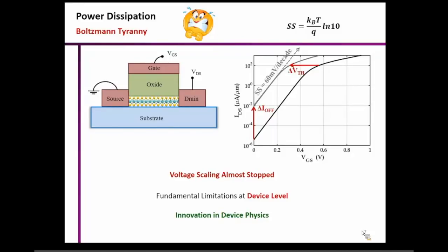And when you do that, you actually run into the problem of high leakage current. That increases your power dissipation in the device. And this is a bottleneck because your subthreshold slope is limited to 60 millivolt per decade by thermodynamics. You can't do anything because MOSFET is the top of the barrier device. Now, if you can envision a device where the subthreshold slope is actually better than 60 millivolts per decade, then you can achieve the same on current, but at the expense of much lesser leakage current and hence much better energy efficiency.